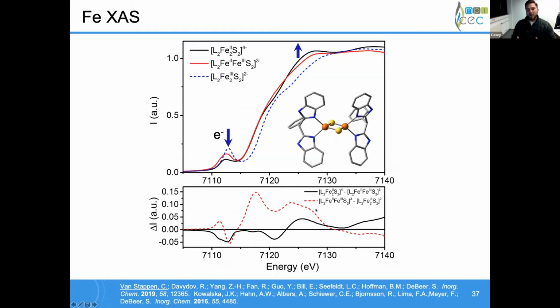If we look at a different system, though, that's not delocalized mixed valent, but localized mixed valent, we can also see much more interesting changes. So instead of just a shift in the edge, which we observe in going from diferric to the ferrous-ferric dimer, when we go from ferrous-ferric to diferrous, we do not have any observable shift in the edge, but instead a decrease in pre-edge intensity, a decrease in rising edge intensity, and an increase in the white line intensity here. So this is what we're going to use as our fingerprint to see what might happen from iron's perspective.